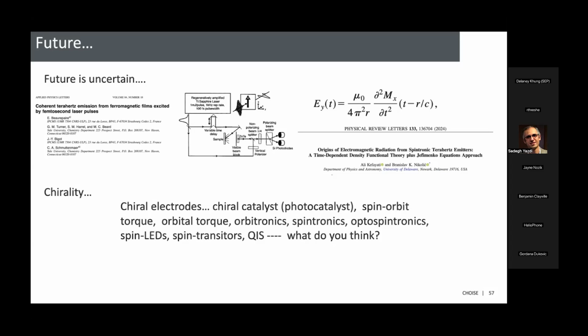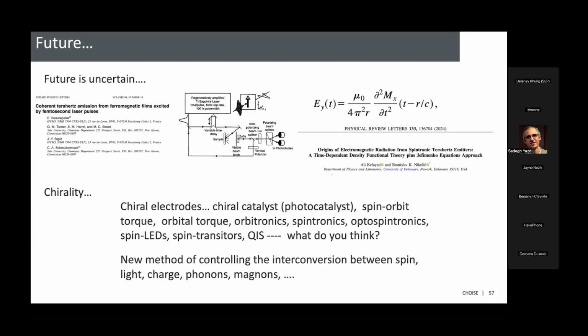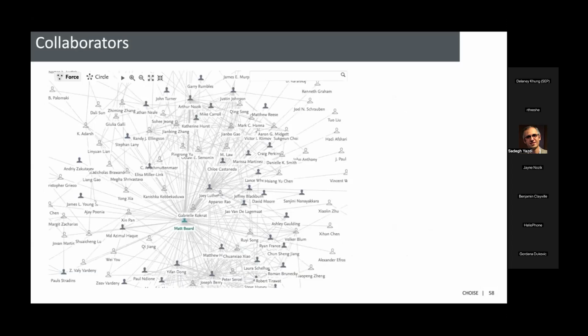Okay, so chirality, chiral electrodes, we talked about this, photochemical reactions are dependent on spin. You have spin orientation out of plane, so that means when the molecule comes down, it can see the spin, it's not in plane, very important. You can have chiral photocatalysis, so water splitting, CO2 reduction are all dependent on spin. You have spin orbit torque phenomena. This is a non-collinear spin orbit torque, if you will. So new kinds of physics here. Orbital torque, I didn't talk about that at all. Orbitronics, spintronics, optospintronics, spin LEDs, spin transistors, impact on quantum information, and of course, your imagination of what could be done with this. All right, it's a new method for controlling interconversion between spin, light, charge, phonons, magnons, whatever.